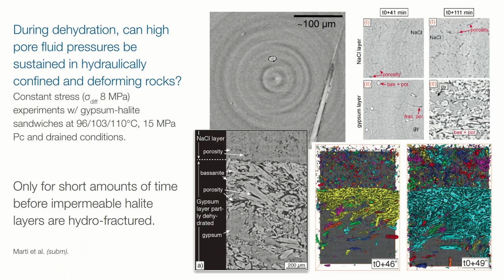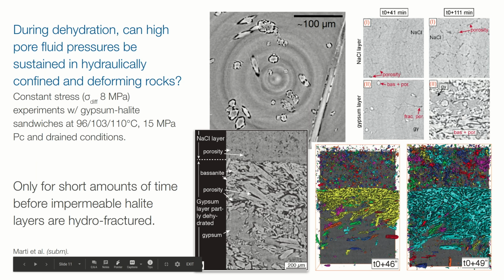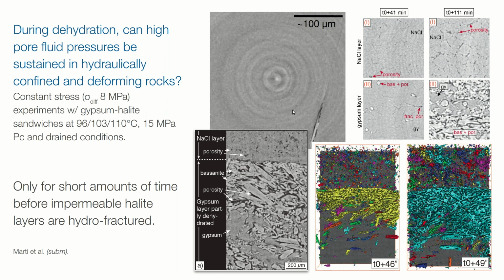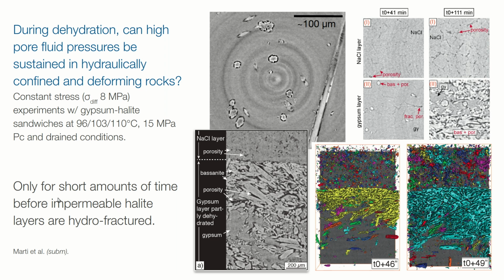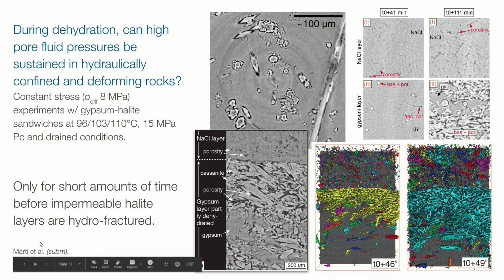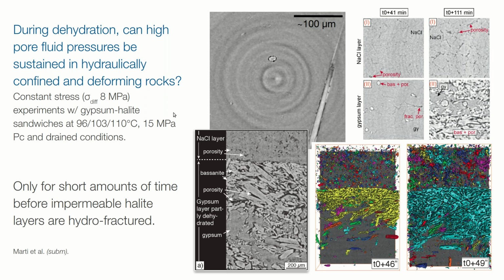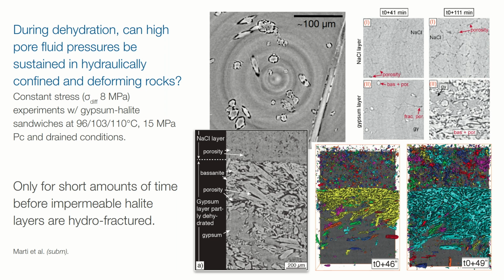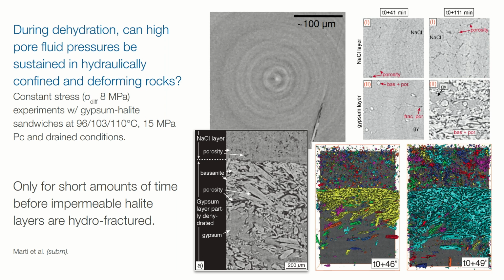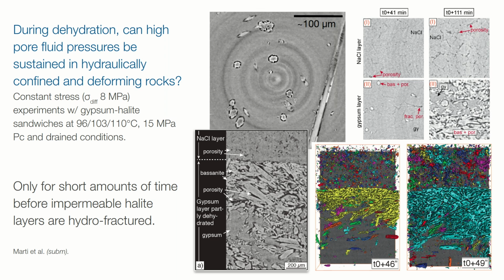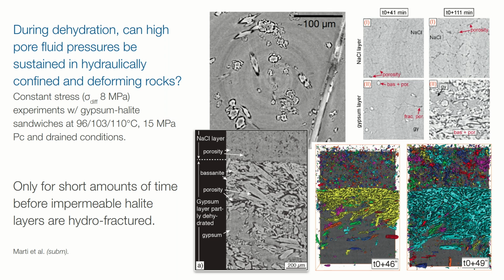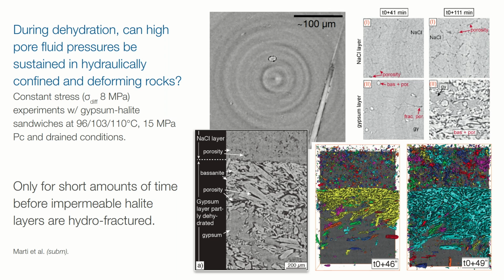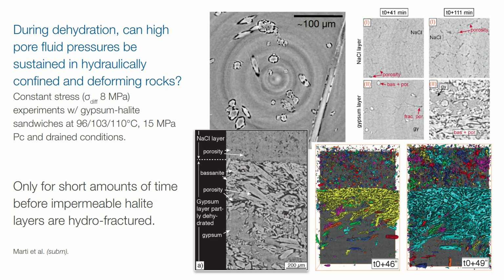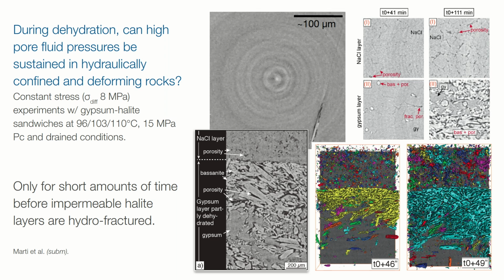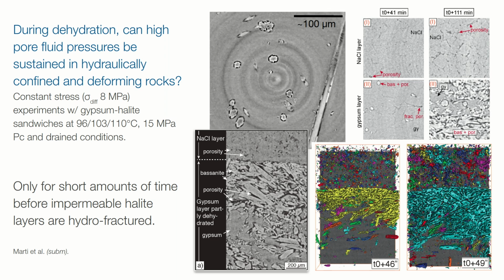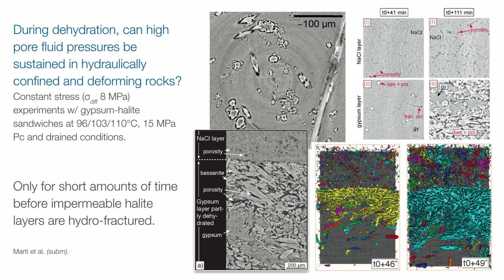Another example here, and I think this is particularly nice in terms of the data quality that we get here. This is another gypsum dehydration example. This is more what I'm working on directly here, and this is work that Sina Marti has conducted, where we looked at essentially the dehydration of gypsum in a setup where the water couldn't drain because the gypsum itself was kept by an impermeable halite layer, which is something that you would expect in natural evaporites. So essentially the idea there was whether high pore pressures that formed during the dehydration, remember that volume difference that I pointed to earlier, whether that high pore pressure can be sustained in hydraulically confined and deforming rocks.